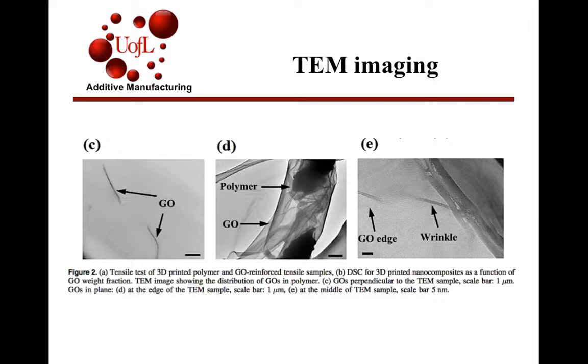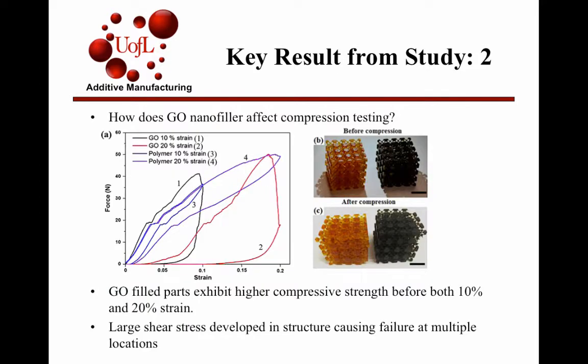And then this picture shows a little bit of the graphene oxide layer with the polymer. This is like a polymer crystal layer, or a crystal chunk. And this one over here shows a little bit more of the linking. They saw what they were expecting to see, in that when you mix the graphene oxide and the polymer together in the ultrasonic thing, the dispersion is kind of random. I mean, it's pretty uniform and random at the same time, if that makes sense. You can't get all the graphene oxide aligned. They're all kind of turned different ways. And so I guess that's good for spreading out the stress inside of the material.